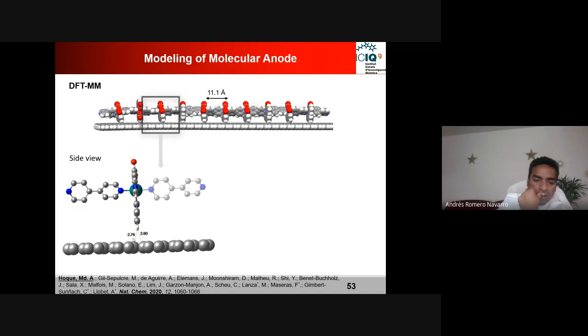Now we found that the distance between this CH bond and this carbon-based material is between 2.7 to 2.8. So this distance is not a direct covalent bond, but it is also not a discrete, separate molecule, because if it were two discrete, separate molecules, then the distance should not be that low. It has to be higher.